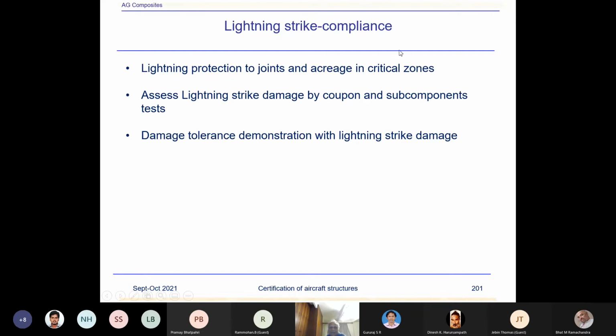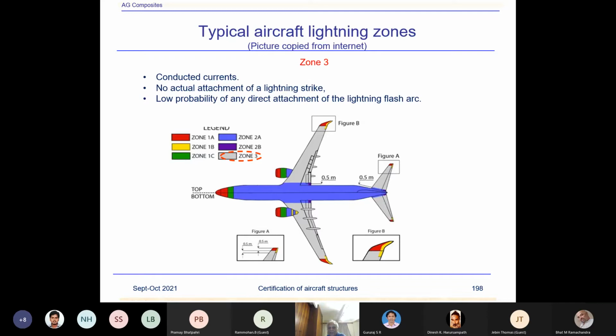So lightning strike compliance is done by lightning protection to joints and acreage in critical areas, assessing lightning strike damage, coupons and subcomponent tests, and damage tolerance demonstration of lightning strike. One of the key areas of lightning strike protection is the fuel tanks, because fuel is located all around the wing, and there's a strict requirement for lightning protection criteria so that the fuel doesn't burn, because there are fasteners which can conduct and then create a flash inside the fuel.